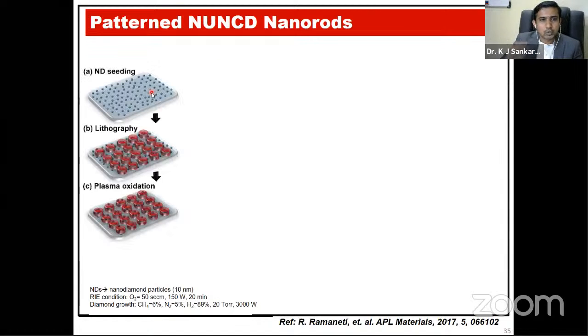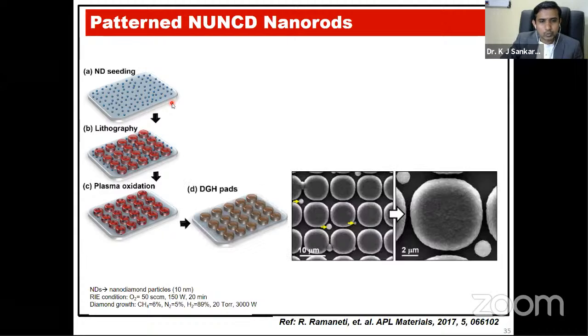The next is the NUNCD nanorods with patterned structures. How we are doing this is that we follow the basic lithography process with the plasma oxidation method. First we use nanodiamond seeding to grow the NUNCD films. So you can see these are the NUNCD films that we grew using this plasma lithography method as a selective area deposition.